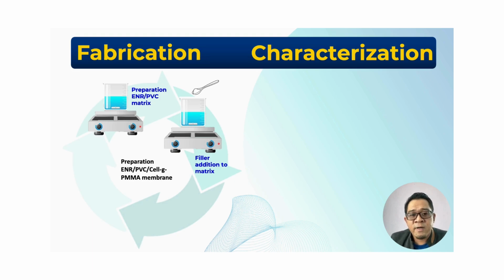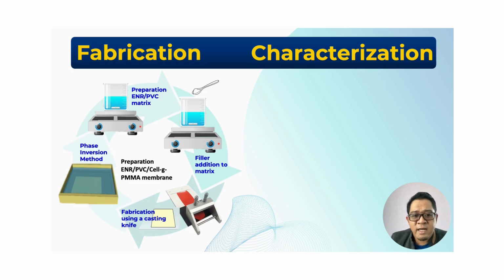10% of grafted cellulose PMMA filler was introduced into the homogeneous ENR PVC matrix solution during the solution molding process to examine its effect on the thin film properties. To make sure the filler is dispersed equally, the mixture is stirred. After that, the solution is poured onto the glass surface and smoothed with a 0.035 mm thick casting knife.